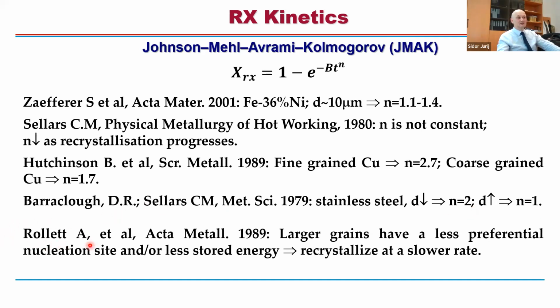And then Tony Rollett and co-authors did simulations of JMAK theory, right? What they claim is that larger grains have fewer preferential nucleation sites and/or less stored energy, and then they recrystallize at a lower rate compared to finer grains. However, we also have to take into account that very coarse microstructures tend to develop shear bands. There is also a famous paper of Davies and Hutchinson, right? And if you have shear bands, then the whole recrystallization kinetics will speed up. For the time being, we leave this n parameter as a fitting parameter in the model.